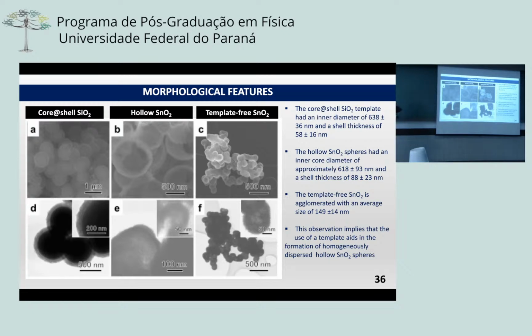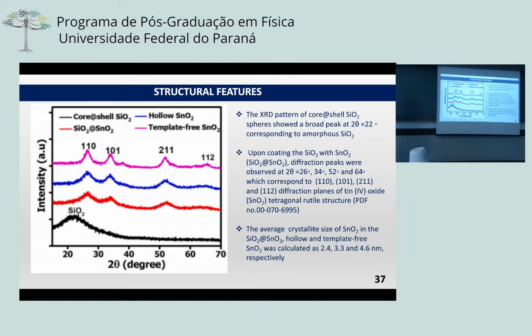And then this is the core shell, as you can see here. Inside it's solid, outside it's a little bit gray, not so black, meaning that it's a shell which is mesoporous. And from there we coated and removed the silica to get these hollow tin oxide spheres. And for the template-free tin oxide, we got agglomerated particles, which were much smaller than the ones made using the template. Looking into their structural features, we did powder X-ray diffraction. This is for the core shell silica. This is after coating with tin oxide. And you can see once you coat with tin oxide, we observe peaks corresponding to the tetragonal rutile structure of tin oxide, confirming that we have coated the surface with tin oxide.